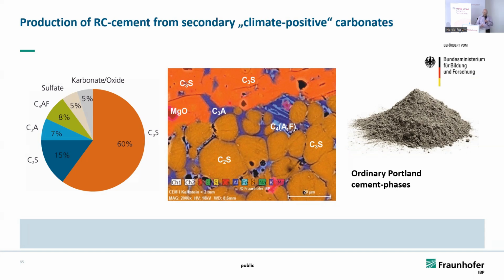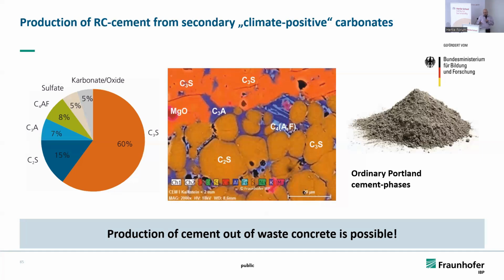But in the last 4 or 5 years, we have found an industry partner who can build generators, which makes it now economically viable. So now we are in the range of an energy consumption of 2.3 kilowatt hours per ton. And we now try to upscale it to about 10 tons per hour. This is a technique, so it is possible to recycle concrete really 100% with this technique. And we have also had many projects with this technology.